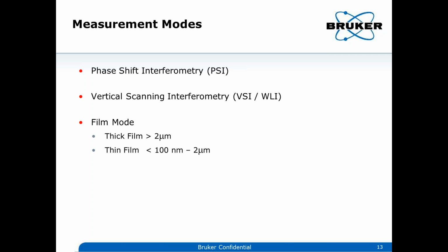And then we have different techniques to measure the thickness of a film. If you have a transparent film, we can measure how thick the film is. We have 2 different modes. To measure thin films, that's like say 100 nanometers to 2 microns. Or if you have a really thick film, greater than 2 microns, you can use the thick film mode to measure it.